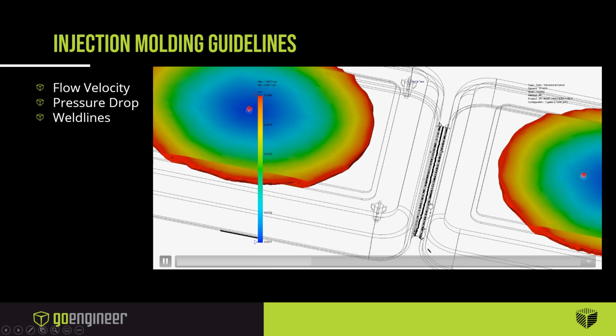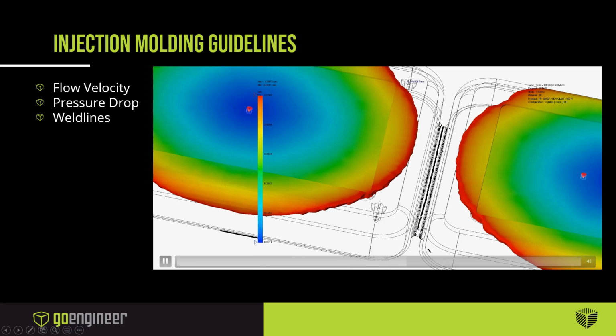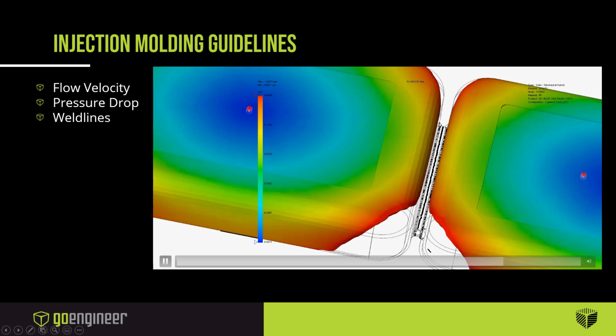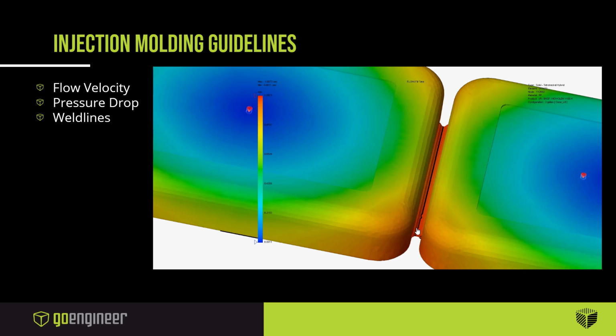If our weld lines come together in the hinge, that's an area where you're trying to flex multiple times, right? So you don't want the weld line to actually happen in the middle of the hinge. If you put your injection locations so that your weld line hits there, you're going to have a weak part. It's most likely your hinge is going to fail.